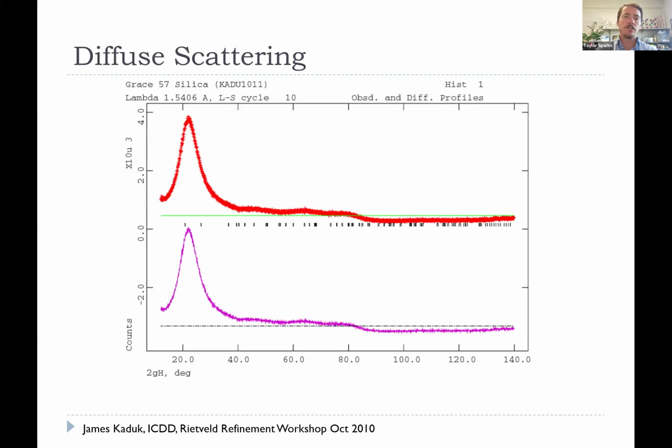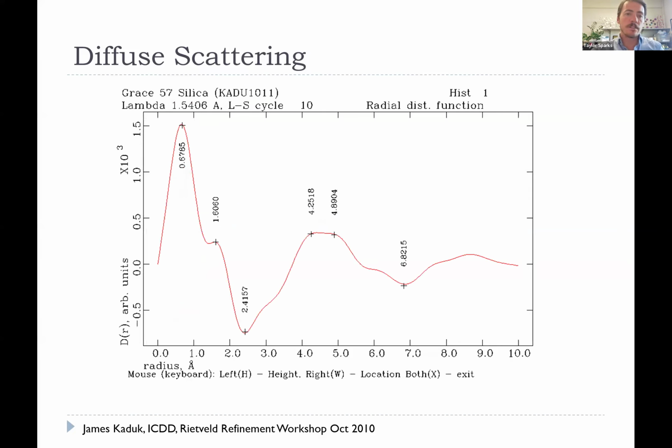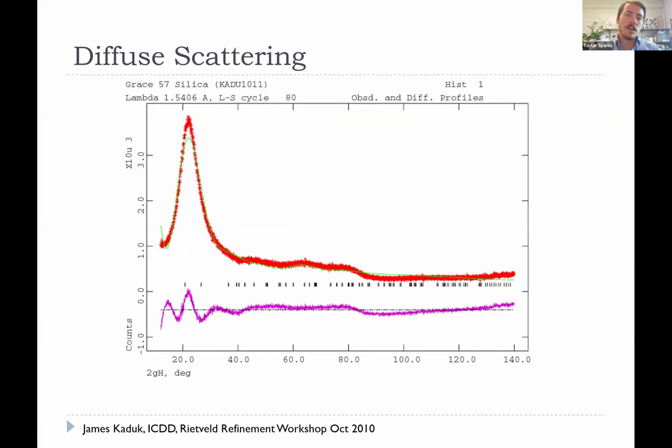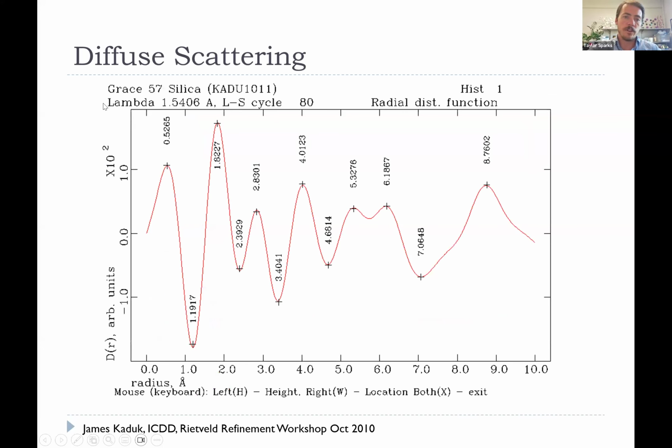So let's say you take a material like this silica glass. It is not crystalline at all. As you can see, when you look at the diffraction pattern, there are no sharp peaks, just one really big amorphous bump. What you can actually do is fit this data and extract a distribution function. What you're seeing here is a radial distribution function that tells you there's a peak in distances, essentially telling you where common distances are, even in an amorphous structure, which is pretty slick.